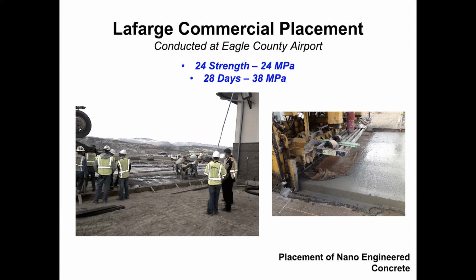And to piggyback on what they said, there are some local contractors around here on the commercial side. I'm not a flat work guy. We pump it. I don't do flat work. I do bridges. So I just put in a big machine. It does my finishing for me. But I will say that from an engineering perspective, when you look at some of these larger surface areas and these larger slabs, if you get your steel right, and then you reduce the cement, you've reduced that shrinkage potential. Now, what you can do, in theory, remember we're all theorists here, you can stretch out your control joints and your saw cuts.